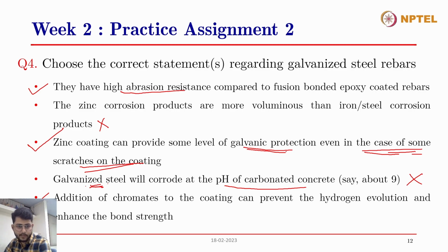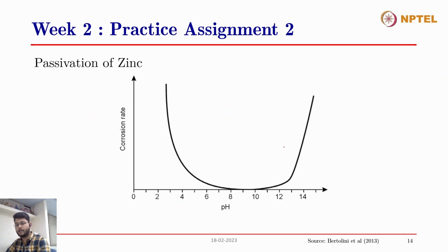The fourth statement mentions that galvanized steel will corrode at a pH of carbonated concrete, say about 9. And this is a wrong statement because, as also seen in the lecture, of the passivation process of the zinc. Whenever galvanized steel rebar is present inside the concrete at a pH of around 12 to 13, the zinc around the steel rebar forms a passivating film, as I have already explained, made of calcium hydroxyzincate, or CHZ.